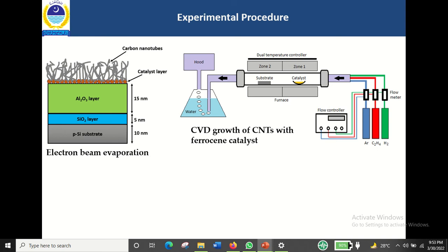The catalyst was placed in the high temperature zone of the reactor and the substrate was placed in the low temperature zone of the reactor, when the ethylene carried by argon and hydrogen as a carrier and the poisoning prevention gases reach the catalyst. It cracks over the catalyst into carbon and hydrogen. The carbon enters into the low temperature zone where it grows on the substrate in the form of a forest.